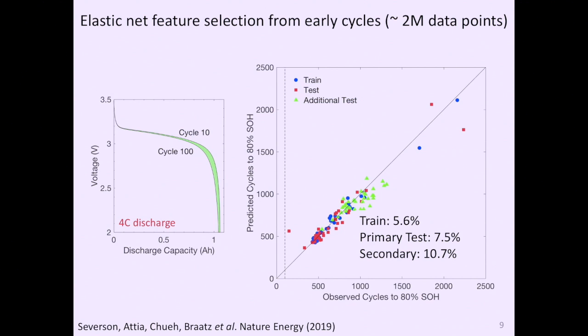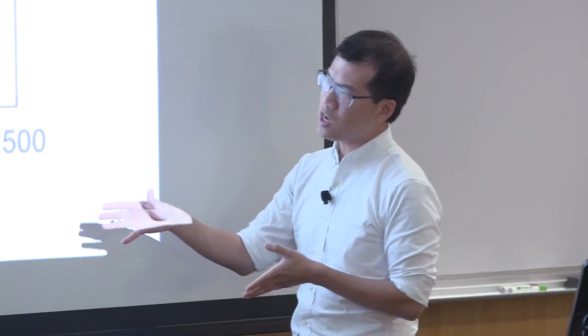So you might say, well, 100 cycles, that's still quite a bit. That's still a couple of days to run. And in a factory, you don't have the luxury of cycling 100 times just because you're eating 100 times into the battery cycle life. So can we do it just with five cycles? So then we changed the objective a little bit. Rather than predicting the lifetime of the battery, I just want to predict whether the battery will be good or bad. If it's good, I will proceed. If it's bad, I will stop.